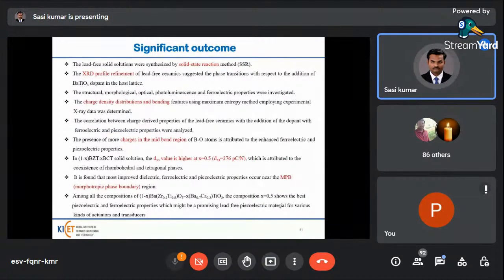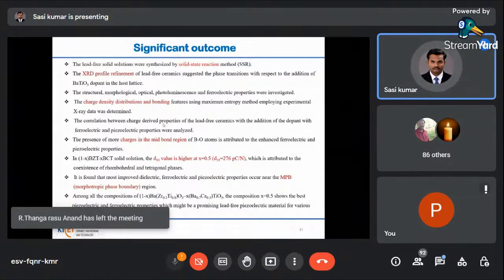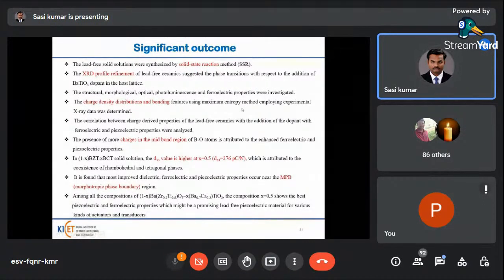And then the significant outcomes from these: lead-free ceramic solid solutions were synthesized by the solid state reaction method, and powder XRD refinement suggested the phase transition with respect to the addition of the dopant in the BaTiO3 host lattice, and then structural, morphological, optical, photoluminescence and ferroelectric properties are investigated. And then charge density distribution and bonding features were studied using the maximum entropy method, employing the experimental X-ray diffraction dataset. The correlation between the charge-derived properties and the ferroelectric and piezoelectric properties of the lead-free ceramics is also analyzed.